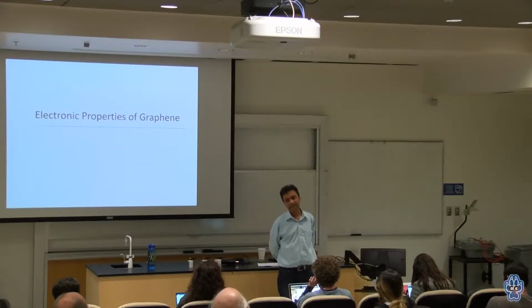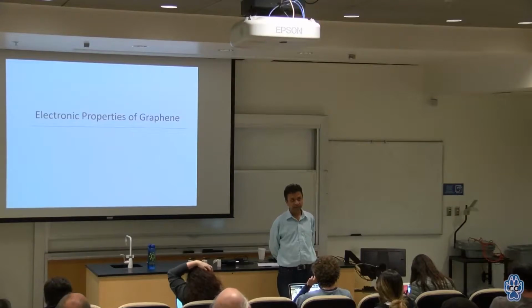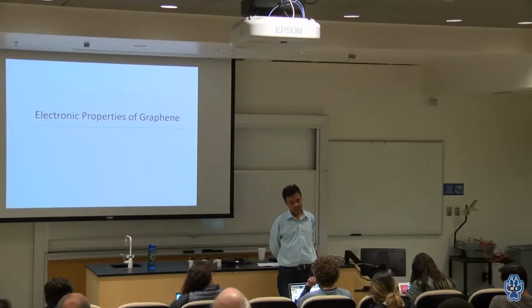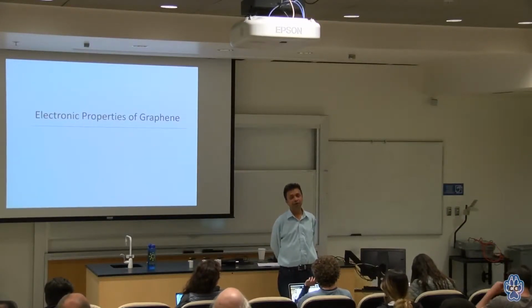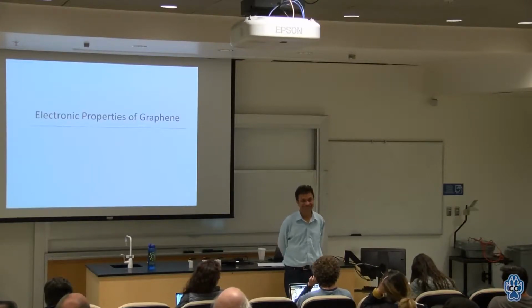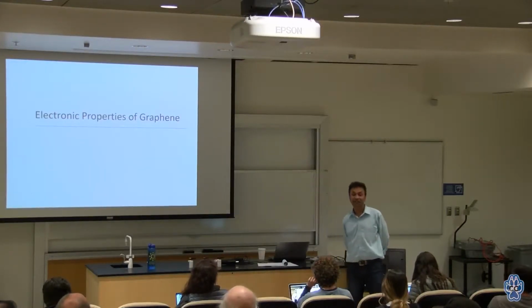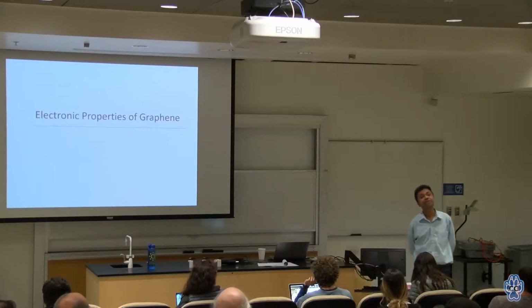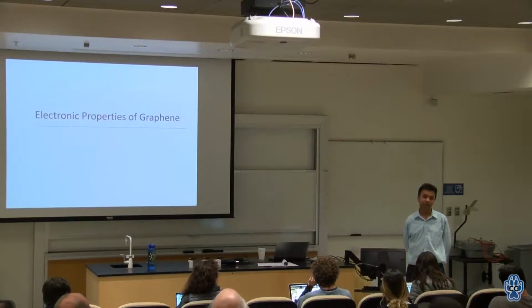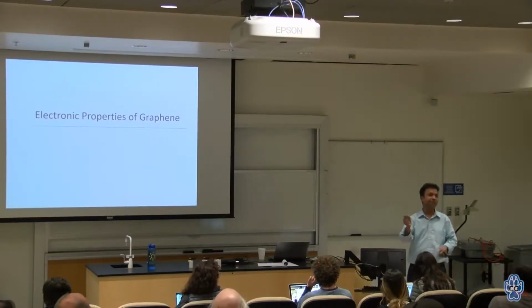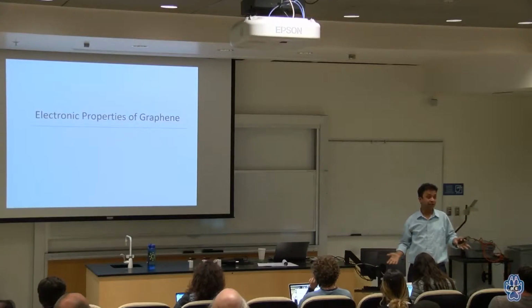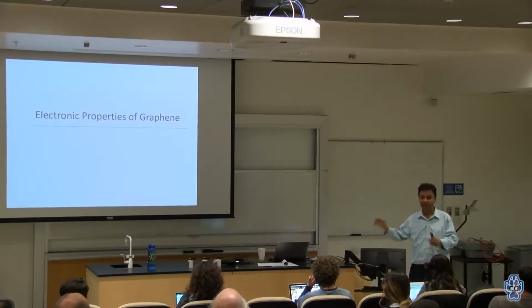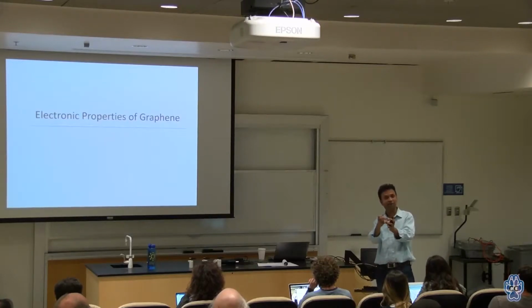Right. And then I'm just wondering about the purity of it. Are we looking for local deformations or inclusions on the atomic scale? I'll talk about some of those. I'll show you how the substrate matters. Indeed, the quality of your electronic device definitely depends on your graphene quality. If you make it using HOPG, you get an order of magnitude better quality than by using CVD, chemical vapor deposition, because chemical vapor deposition has lots of grain boundaries in it.